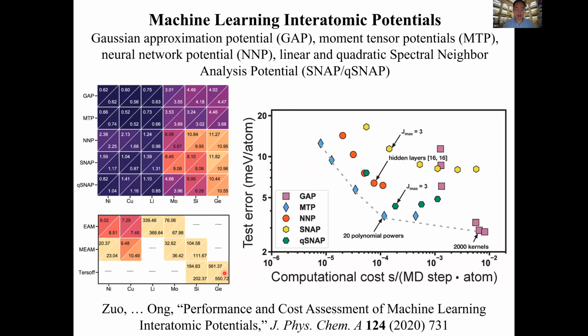I think this is some kind of mean average error. And what you see, and this conforms with my experience as a grad student using these potentials, is that you're dealing with really huge, hundreds of meV per atom errors. But once you switch to these machine learning potentials, then you have at least an order of magnitude improvement in these energy errors.